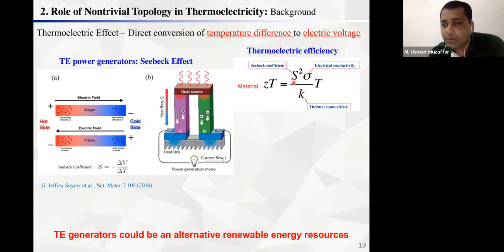If we want to enhance the efficiency, we need to enhance the power factor. This is the power factor, which is the product of the Seebeck coefficient and the electrical conductivity, and we need to decrease the thermal conductivity. But unfortunately, these three parameters are interconnected with each other.